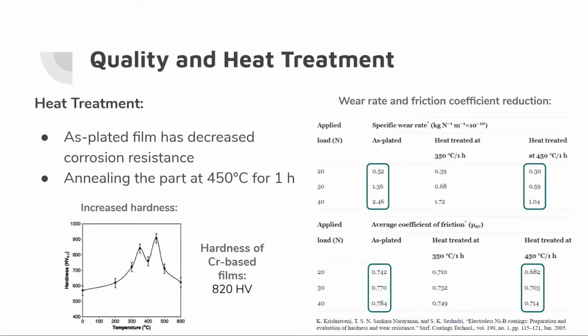As you can see here in the graph, the hardness will be increased to up to 900, which is slightly higher than the chromium-based coatings, which are about 820 in the Vickers range. As a result of this improvement, we will also decrease the wear rate and the friction coefficient, as you can see in the tables at the right, which will improve the durability of the coating.